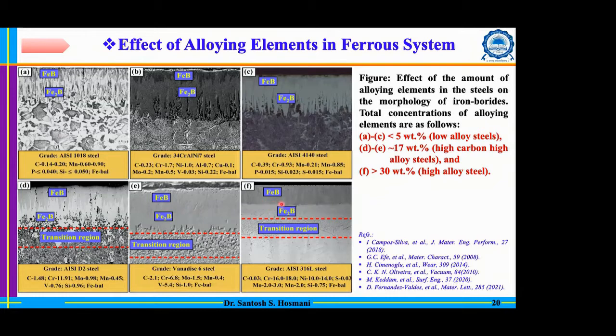And you can see the interface between these, that is the interface between Fe2B and the transition zone, as well as FeB and Fe2B. It is quite smooth in nature. That means the morphology of these borides is significantly dependent on the concentration of this alloying element, apart from the effect of the alloying element on the migration behavior of these borides. So along with that, these two important effects are basically governing the morphology of these iron borides.